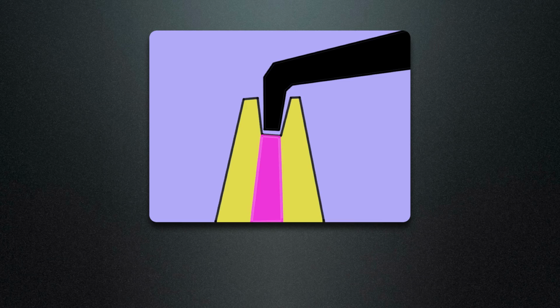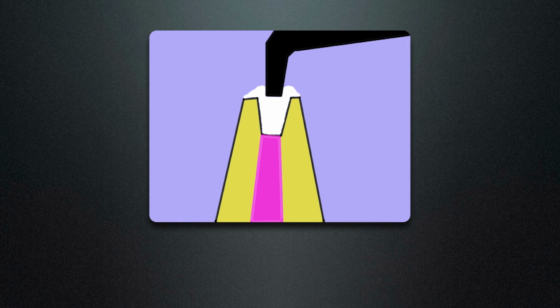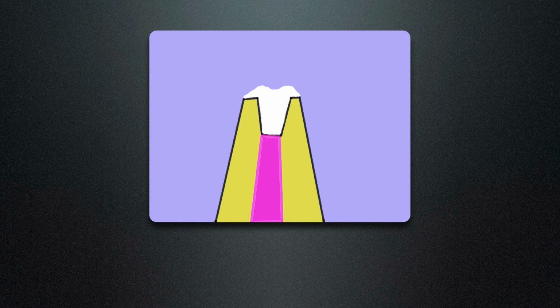You don't have to wait till the putty sets. You just basically place it and you're done, which means that your retrofillings are going to take a tremendously shorter amount of time nowadays to complete than they did before. When you use MTA or amalgam, any other material, you had to serially condense the material. Now you basically inject the syringeable material, which could be either the sealer or the RRM syringeable, and then just place a thin cap of the fast set putty up on top of it to protect it while it's setting.